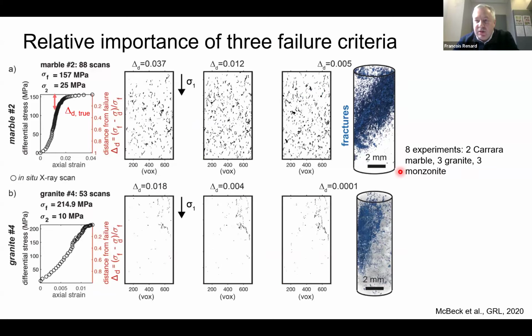So that was logistic regression, which, for me, was very close to statistics when we did that. Let's go to level 2. So level 2 is gradient boosting machine learning. Again, we start with experiments, the same set of experiments. Here we have 8 instead of 4. So we have all these circles, it's a 3D volume, a bit like that. And we measure the distance to failure through this parameter. When it is 0, the sample is failing. And when it is 1, it's far from failure.